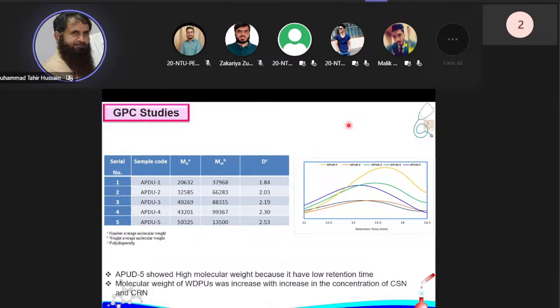After that, we studied our material using GPC studies, and we determined the number average molecular weight, the weight average molecular weight, and the polydispersity, that is the ratio of Mw and Mn. We found that the material with high concentrations of chitosan and curcumin shows the highest molecular weight, as is also apparent from the GPC chromatogram, because the retention time of this material has been reduced. So APUD5 showed the highest molecular weight because it has a low retention time, and the molecular weight of the polyurethane dispersions increased with the increase in the concentration of chitosan and curcumin.